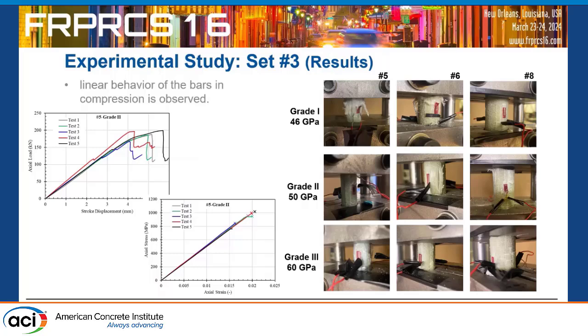Strain gauges provided a very consistent slope, and sometimes strain gauges go away. For example, at 15,000 microstrain, and then we have the load. The cross on the axis shows the final point. That's the output where we put two strain gauges and averaged, but most of the time we had two very consistent strain gauges, literally very similar.